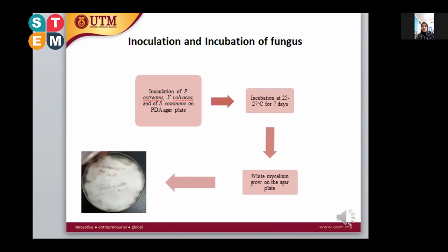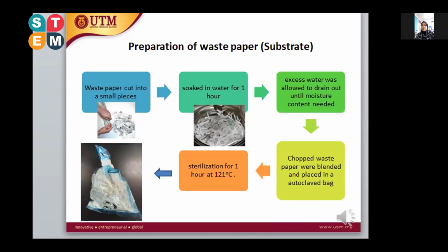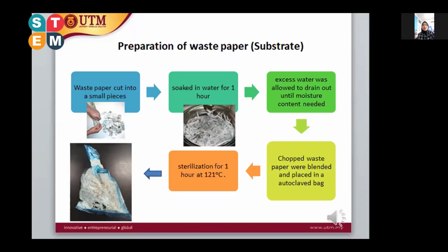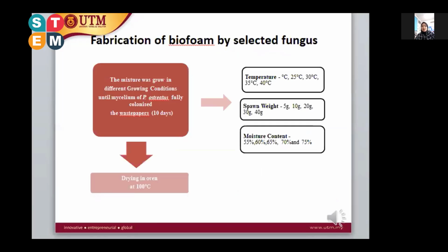Okay, here is the methodology. First, we begin with the inoculation of the fungus on PDA agar plates, and then we incubate them following a standard procedure for 7 days to form mycelium. The waste paper is prepared by cutting and soaking it in water for 1 hour, and then we chop and blend it and place it in an autoclave to sterilize it before we use it to culture the mycelium. Next.